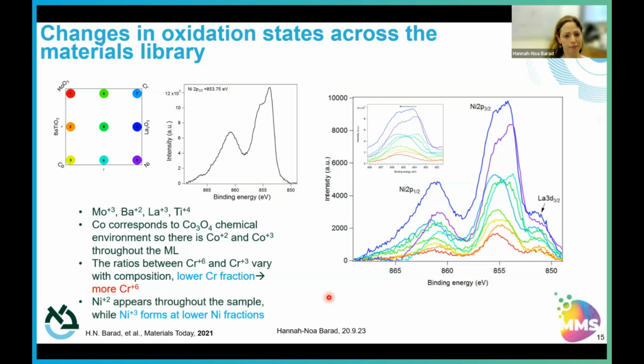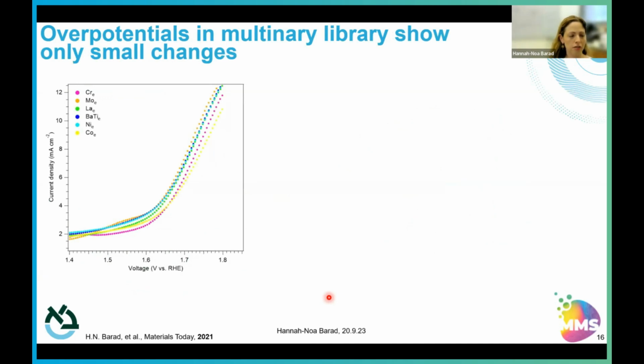So of course, once we investigate these materials and look at their characteristics, and we see that they're both compositionally varied and also nanomorphology varied, and as well varied in oxidation state in our case, then we looked at the electrochemical characterization. So these are just LSVs from the edges. We did, of course, full material library scans. But you can see really just from the edges that there really is almost no variation. I mean, this is within the error limit, of course, between the different edges, which was quite surprising to us because we thought to ourselves, well, we have variation in nanostructure, we have variation in composition, we should see a difference.